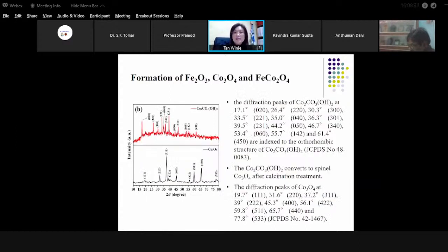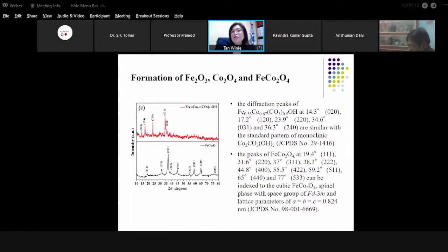We also did the same check of the structural properties of the cobalt oxide. These are the diffraction peaks of the precursor, cobalt hydroxyl carbonate, which after matching with the library are all indexed to the orthorhombic structure. Then the precursor converts to spinel cobalt oxide after calcination, and the diffraction peaks are identified using the library. These are the diffraction peaks of the precursor materials for the iron cobaltite, which are similar to the standard pattern of monoclinic cobalt hydroxide carbonate.